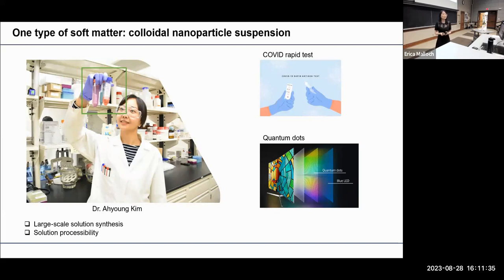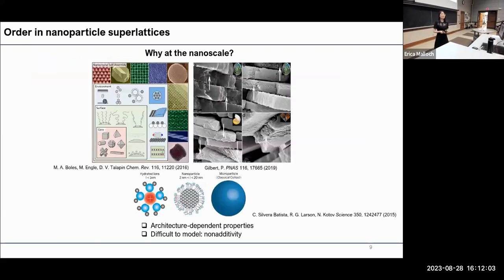Those colloidal nanoparticle solutions are very intriguing materials because they can easily be synthesized on a large scale in solution. They have solution processability, and they can also have composition-, size-, and shape-dependent properties. For example, the red lines you see in the rapid COVID test are the color of gold nanosphere solution. And now you can see more and more quantum dot-based TV displays out there. In the context of colloidal nanoparticle solutions, ordering is a very intriguing question, as beautifully demonstrated in this Chemical Reviews paper. This is because the periodic superlattice self-assembled from colloidal nanoparticles can have architecture-dependent optical, electronic, and catalytic properties. And broadly speaking, in nature, a lot of biominerals are essentially composed of nanoparticle building blocks.